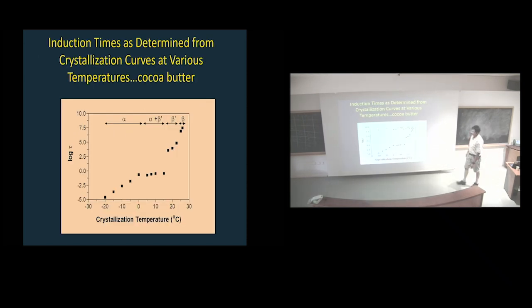And because I was very lazy, I didn't calculate the free energy of nucleation. But here are the induction times. And look how much, if you crystallize cocoa butter at different temperatures, you can see how the induction time of nucleation is really related to the alpha polymorph, a mixture of the two, the beta prime polymorph and the beta polymorph. Yes, sir.